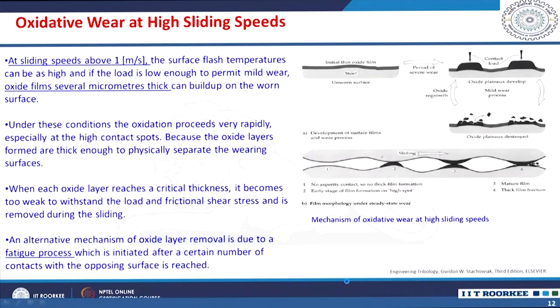Because these oxide layers formed are thick enough to physically separate the wearing surfaces, you will have a mild wear, right? The initial thin oxide film is subjected to contact loads and the material is removed, and again oxide is regrown. When each oxide layer reaches a critical thickness, it becomes too weak to withstand the load and frictional shear stress, and so is removed during the sliding, right?